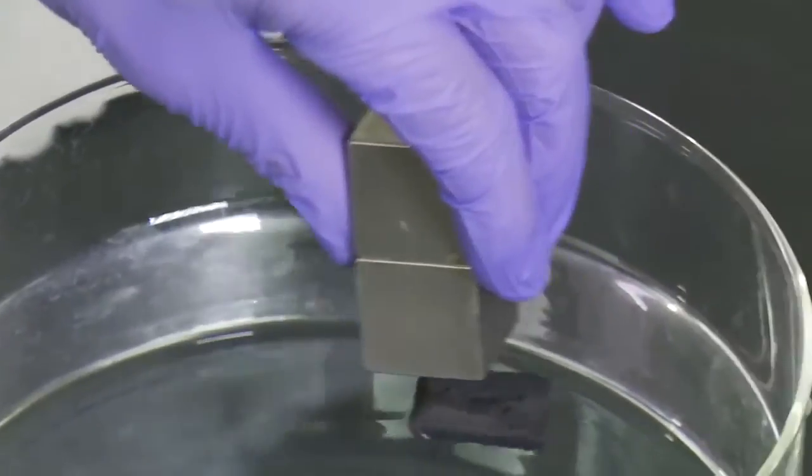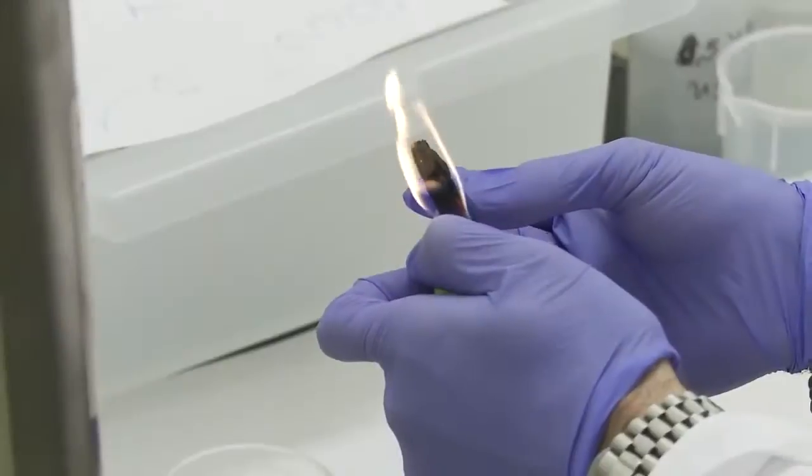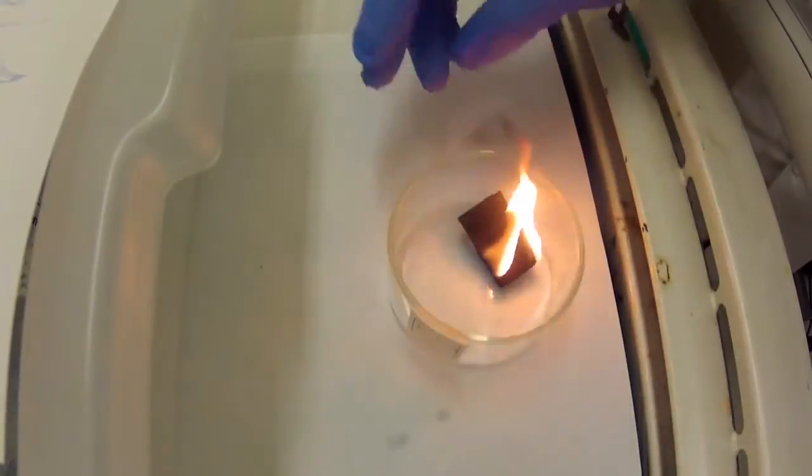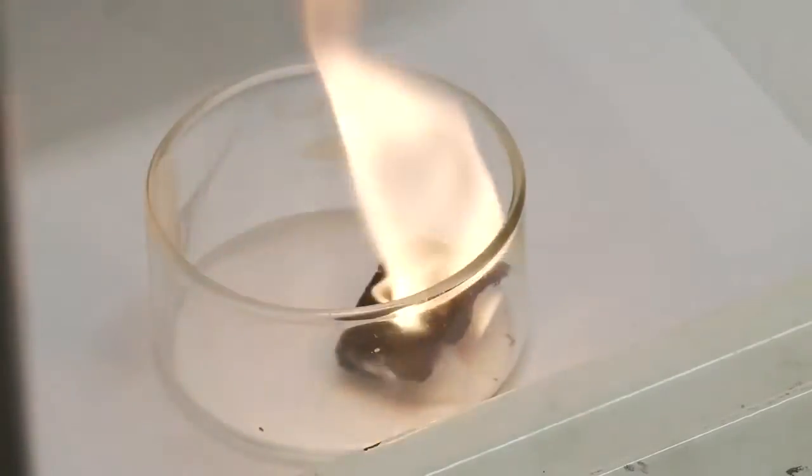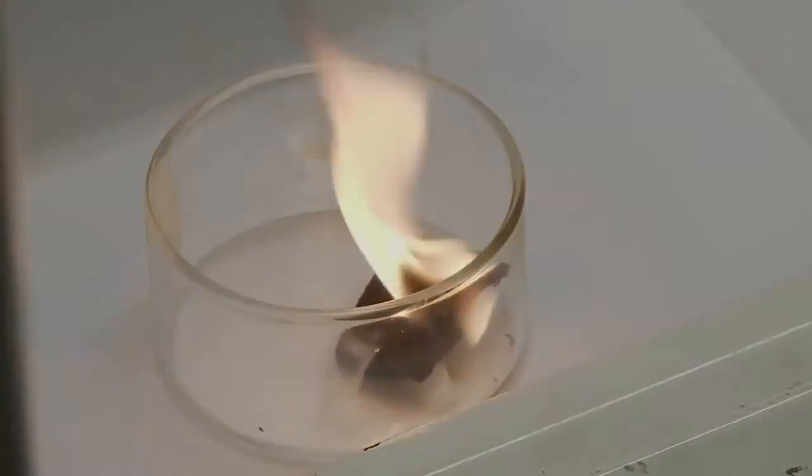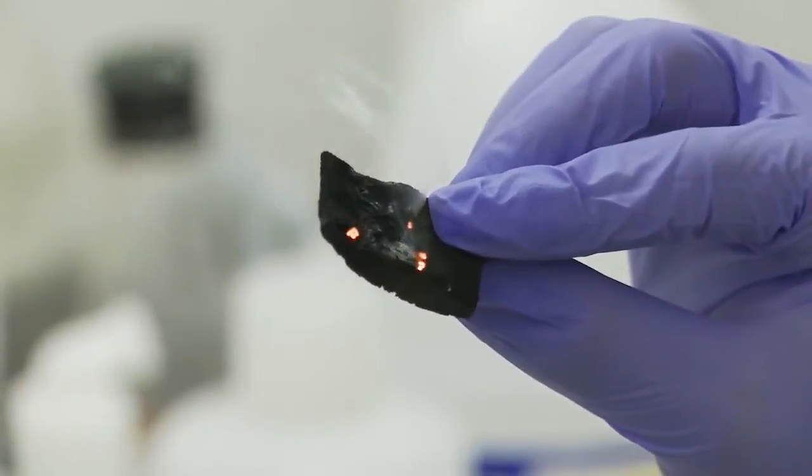After saturation, the oil can then be burned out while the carbon nanotube structures themselves remain intact. The oil protects nanotubes from significant oxidation during this process, and once it has been burned away, the nanotubes quickly drop below the oxidation temperature.